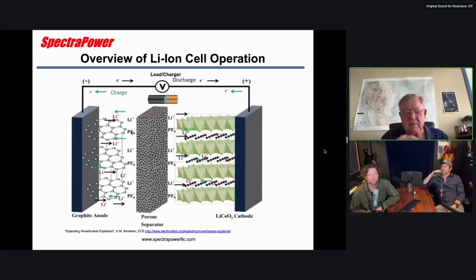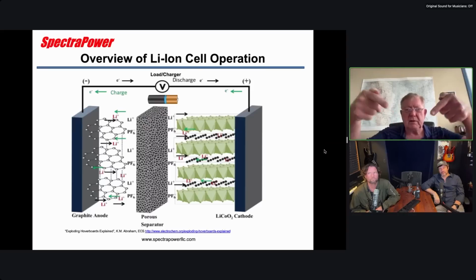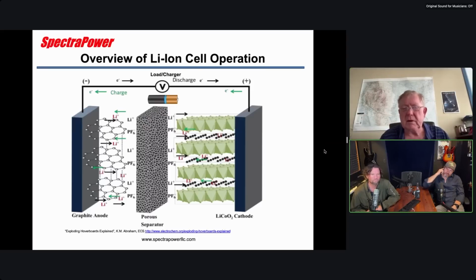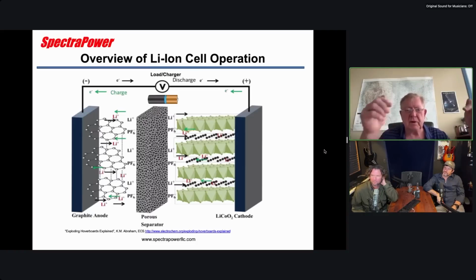When you don't, lithium forms what are called dendrites. They're like sharp needles of lithium. The reason those form is that anytime you have a little bit of a high surface on this lithium metal, it causes the charge to focus into that one point. Then it deposits and builds and builds until you get this very sharp needle. It's like a nucleation site for crystallization. Yeah, the field lines focus into that point, and everything goes to that point.